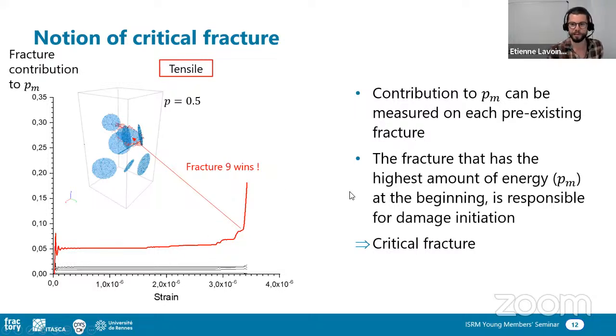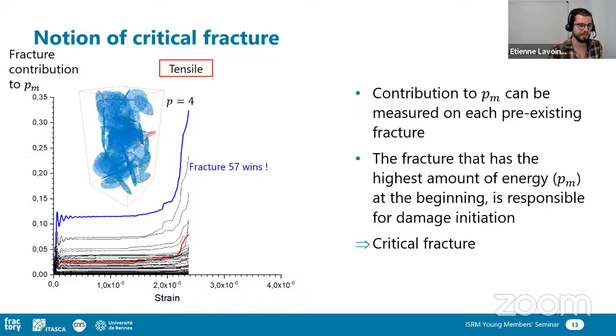So what we can see here is that the fracture that has the highest amount of energy, that is quantified with the PM parameter at the beginning of the simulation, is responsible for damage initiation. So here, because the fracture is almost horizontal, the loading on the fracture is quite important, and we have the highest amount of energy, so the highest amount of stress redistribution around there, and the matrix starts to break around this fracture. So this is what we call the critical fracture. But depending on the network, this is not always the same fracture. So, for example, another fracture wins the race because the geometrical configuration enhances the energy on that fracture.